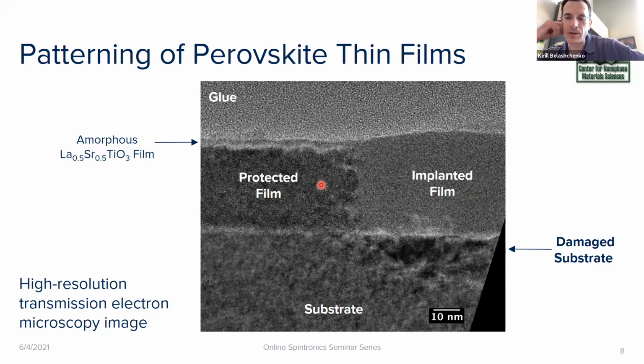This is what I was going to ask about: you can have magnetostructural coupling, but then it might depend on the sign of the coherency strain. So you could engineer structures with a different sign and check if your pattern actually switches from orthogonal to parallel. Right. So we've only done this on strontium titanate substrates, and these are actually niobium-doped strontium titanate substrates, and we do that because of all the charging reasons that I was talking about with Xiao, that it helps to have a conductive substrate.